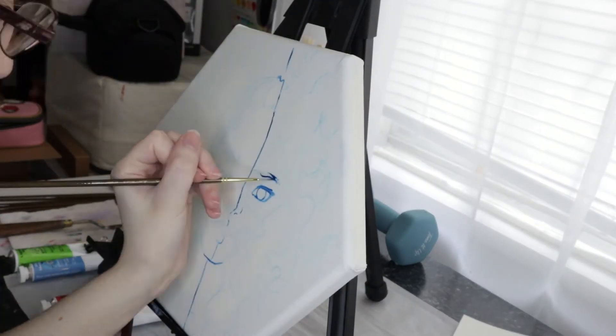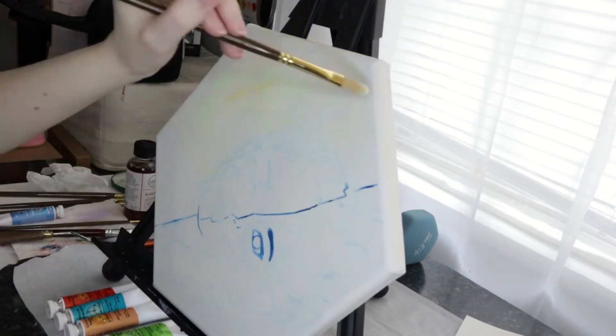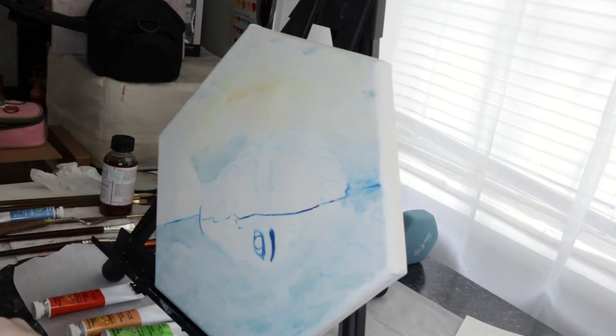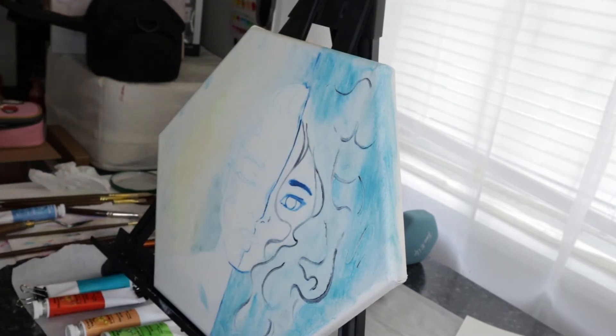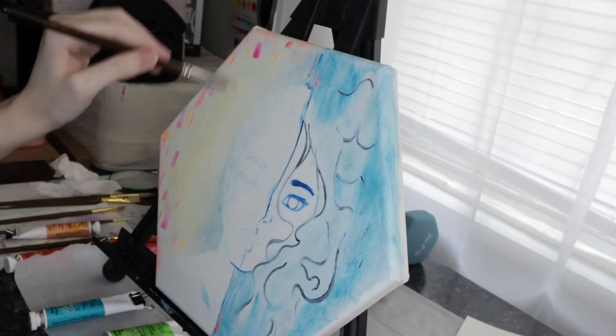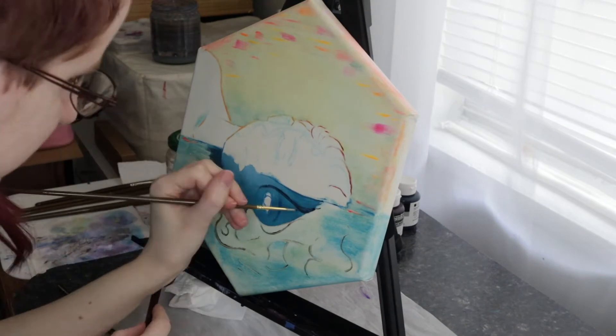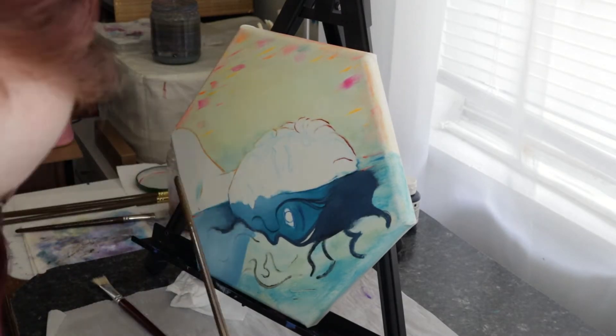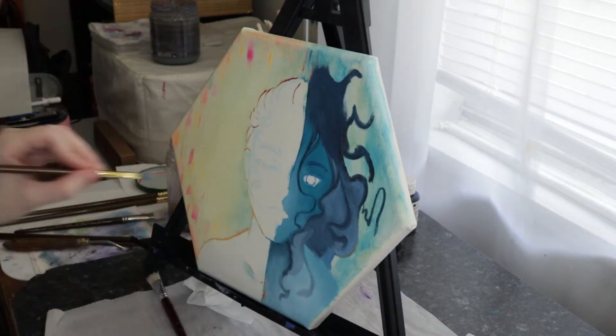In the painting I'm working on, I wanted to challenge myself to use just the glow-in-the-dark paints only, but it was proving to be ineffective for painting the composition that I wanted. So I brought in my regular oil paints for painting the figure. I started with a layer of just Lightning Bug for the background because I wanted bits of glow to potentially pop through, but in the end I don't think that actually showed through at all. These paints can be paired, layered, and even mixed with regular oil paints. If you're going to mix them, Russ suggests using only a small amount of transparent oil paint to tint the glow paints, since opaque pigments will interfere with the UV light reaching the photoluminescent particles. This paint can also be mixed with oil mediums such as Galkyd to reduce drying time, which is something I relied heavily on for this painting.